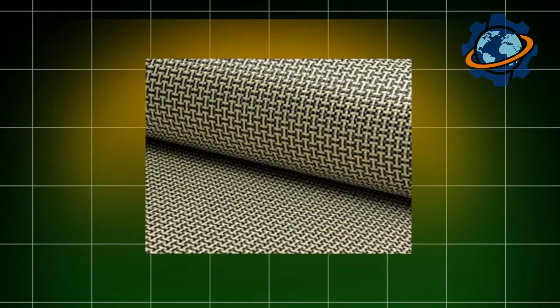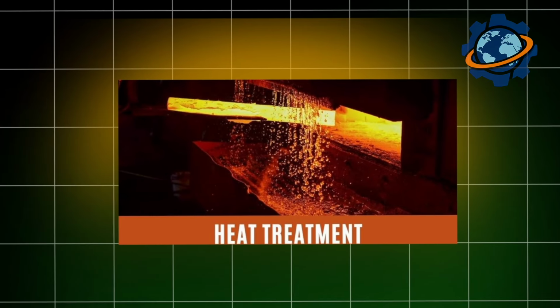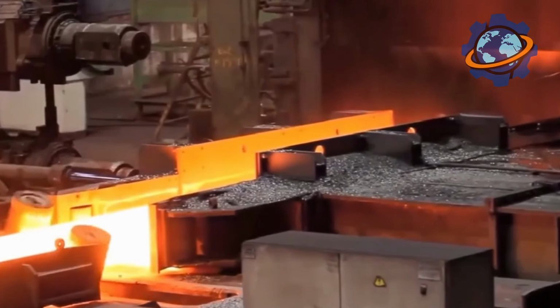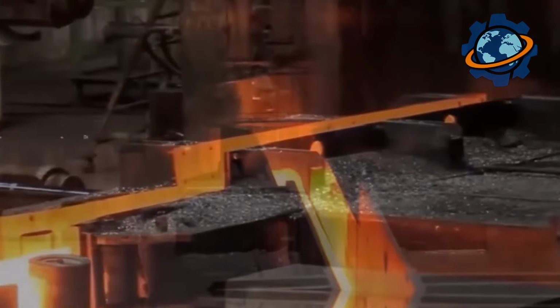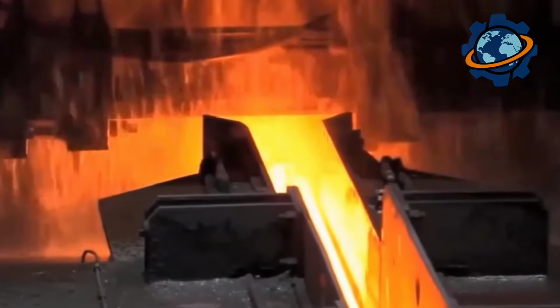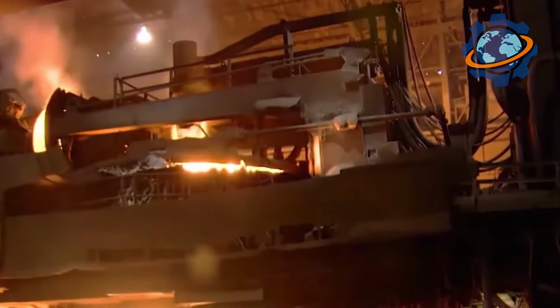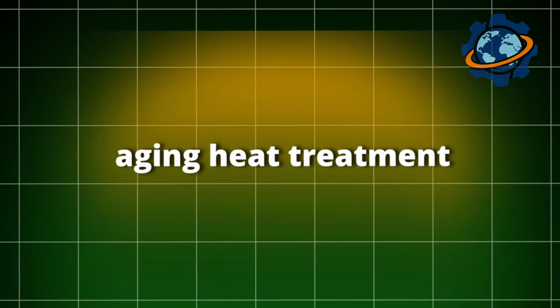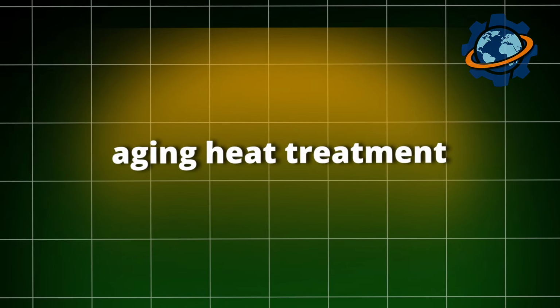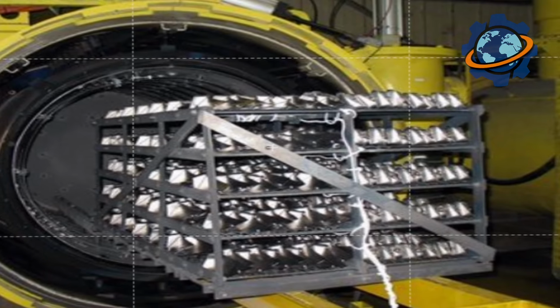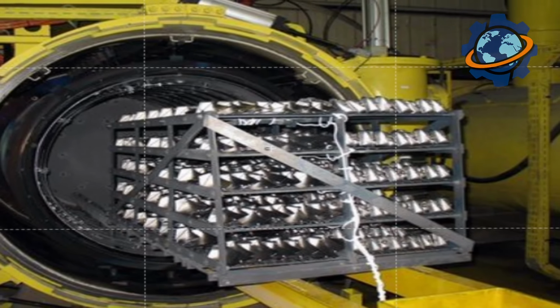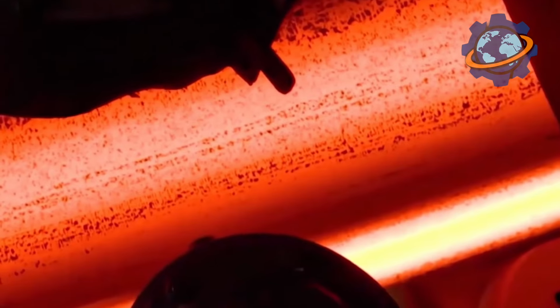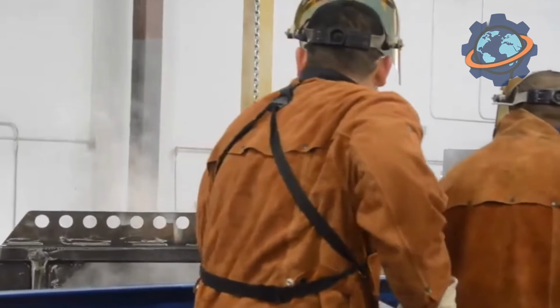geometric formation. After solidification, blades undergo solution heat treatment at 2,200 degrees Fahrenheit for 2 hours, then quench in inert gas. This locks crystal structure permanently and precipitates microscopic strengthening phases throughout the lattice. Next comes aging heat treatment, multiple cycles at precisely controlled temperatures that cause nanoscale particles to form. These particles, called gamma-prime precipitates, occupy 70% of the alloy's volume. Picture this. Imagine a 3-dimensional checkerboard where hard particles pin the crystal lattice, preventing atoms from sliding.